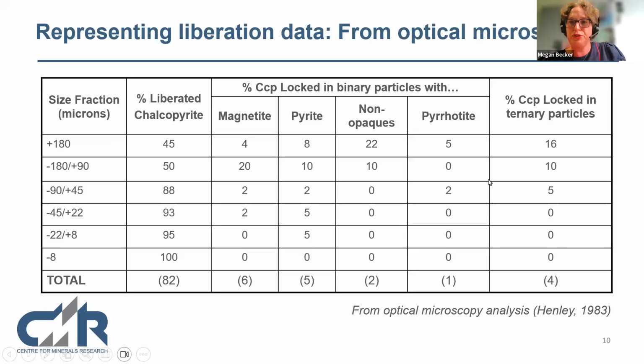Okay, so I just wanted to show you what some of the original liberation data look like. This would have come from optical microscopy. This comes from the 1980s, and they looked at chalcopyrite. If the chalcopyrite wasn't liberated, they looked at, in terms of binary particles, what other mineral it is associated with. And if it didn't fall into that category, then it goes into a ternary particle. Obviously, this is done on a size-by-size basis. We get better quality data and more confidence in the data when you do it sized, but it also provides more information. Then we know the unliberated material is sitting in these size fractions, and those are the ones you need to grind finer or something like that.